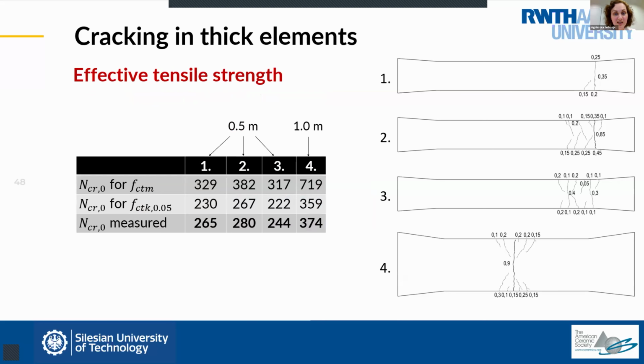And the final observation that has been made over this research is that actually cracking is, let's say, a statistical process, and that the cracking in an otherwise uniform element will happen in the weakest cross section. So I would call it the weakest link theory. It means that when we have a tie, which we would say is normally uniformly loaded, since concrete is not a homogeneous material, it's a highly heterogeneous material, we expect the crack to happen in the weakest section, which might result from many things, like location of aggregate or poor workmanship, which results in this heterogeneity.